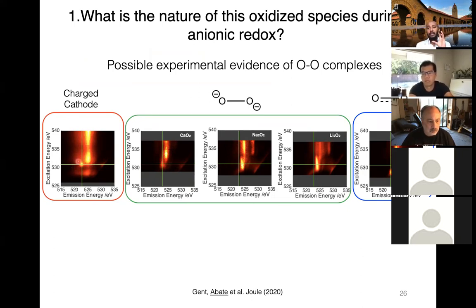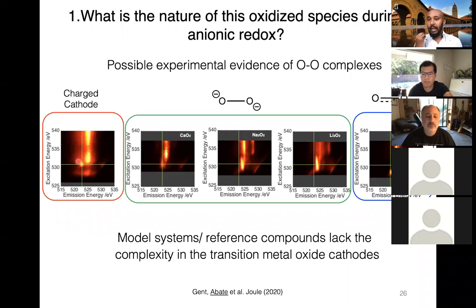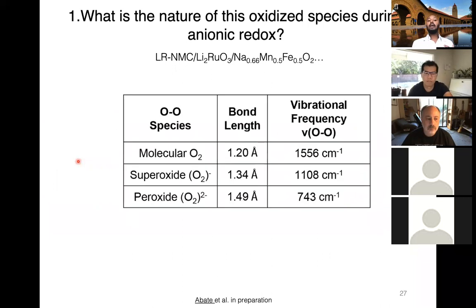However, both these compounds we use as reference compounds for measurement or for simulation don't have a transition metal, which is the biggest component of the cathode material we use. Because of this lack of transition metals, they lack the complexity of metal-oxygen hybridization. Therefore, these results are preliminary but not conclusive. So what we decided to do moving forward is to further resolve the different oxide species using either their bond lengths or their bond vibration.